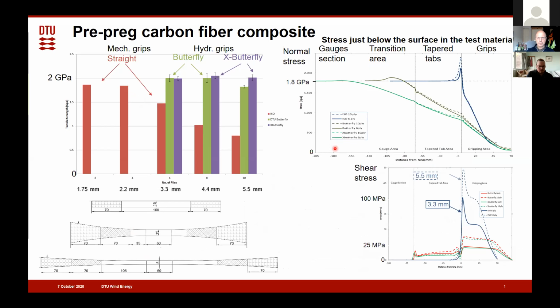So what is the reason for this? If you do a simple stress analysis of the 3 geometries here, then the blue curve here corresponds to the rectangular sample, and the green curve is to the long butterfly sample. So this is the normal stresses in our sample. We have some stress intensity where we have the end of the tab material. For the other 2, we have tapered tab material here going from 2 millimeters thickness down to 0 thickness here. And we can see there's also some stress intensity here, smaller for this one. I have here shown the normal stresses just below the surface of our test material.